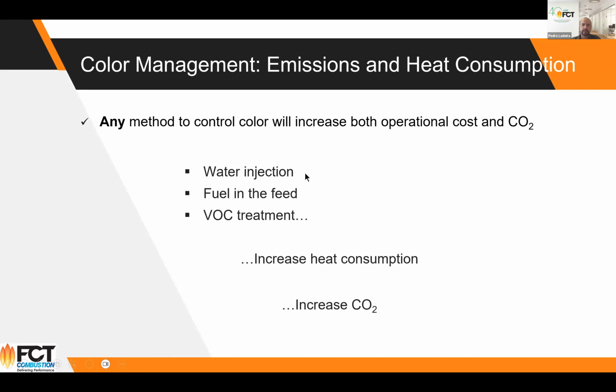You can imagine when you add water to a kiln, you're going to increase the heat consumption, and as a consequence, the CO2 emission. The fuel in the feed also you're going to increase because not all the energy is being used by the kiln, and then you're just wasting some fuel by adding it to the feed. And not to mention the VOC treatment, because you're putting fuels in the inlet, and then you have VOC emissions in the exhaust gas. All this will increase your heat consumption. All of this will increase CO2 emission. But still, if you want to do this, I would like to compare the methods.